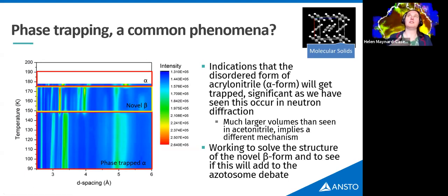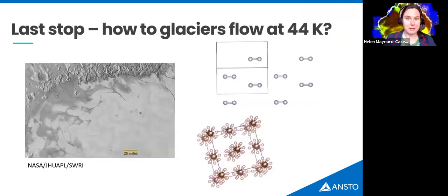So with the acetonitrile, we hypothesized that the phase trapping was happening because of a strain from these really tiny capillaries. The capillaries we use for that are only 0.3 millimeters. In this sense, this is both a disordered thing, whereas acetonitrile is not disordered, but also it's happening on a bigger sample. So the mechanism of this phase trapping is very different. So that's something that we've definitely got to delve into a bit more.